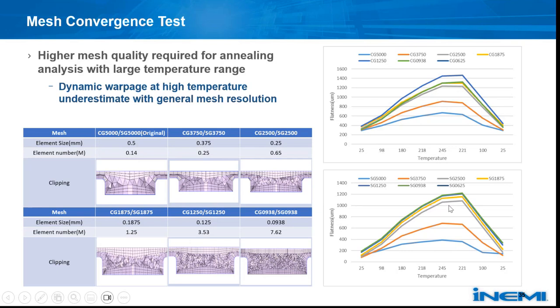We also find that the convergence mode is a little bit different between the center gate model and the side gate model. Also, the flatness at room temperature increases as we decrease the mesh size, but it is much smaller compared to the increase of the flatness at the high temperature. Next page.